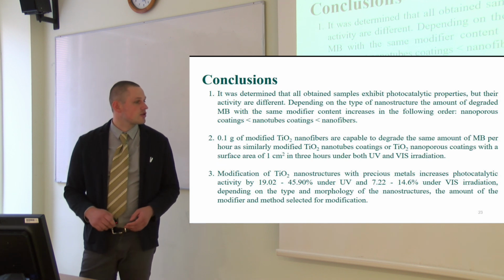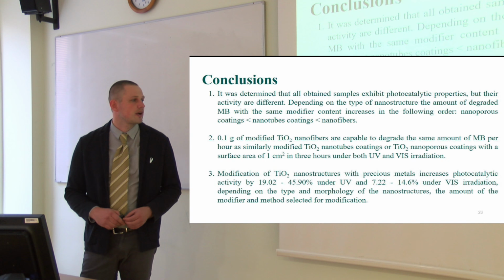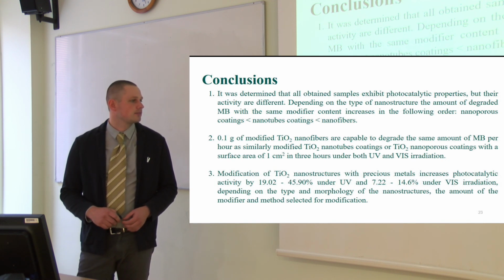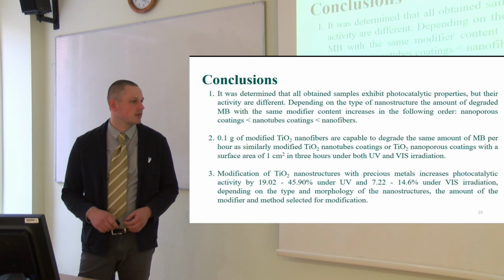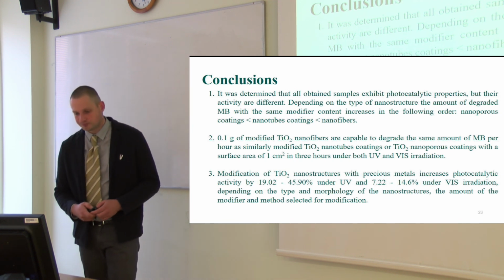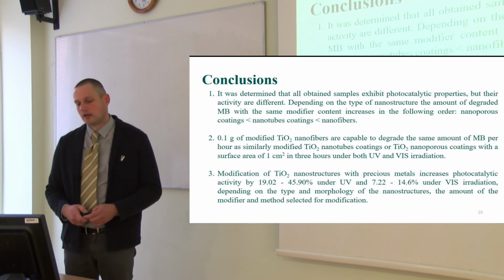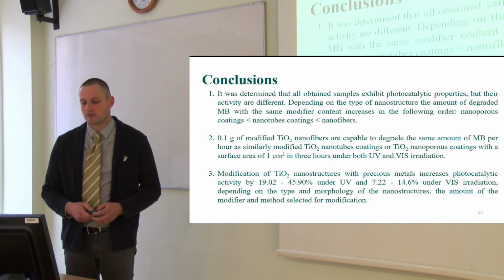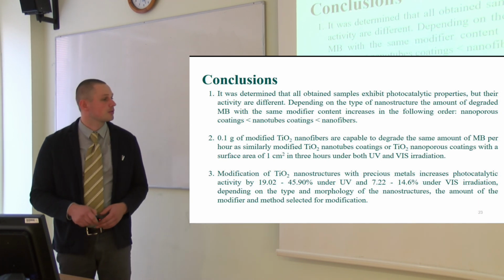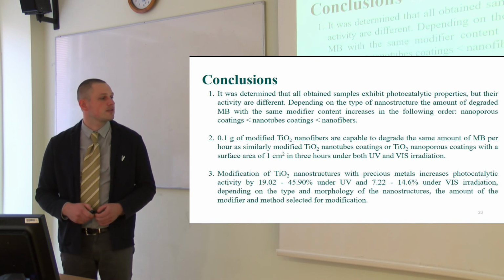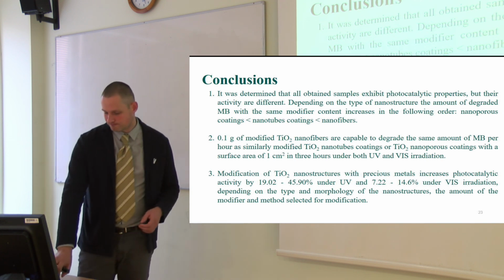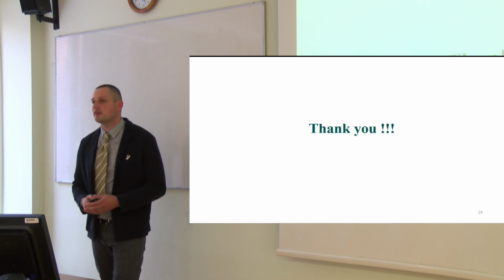And it was measured that photocatalysts that are modified with precious metals can degrade up to 45% more methylene blue solution than pure nanostructures, and up to 14.6% in visible light irradiation. So thank you for listening.